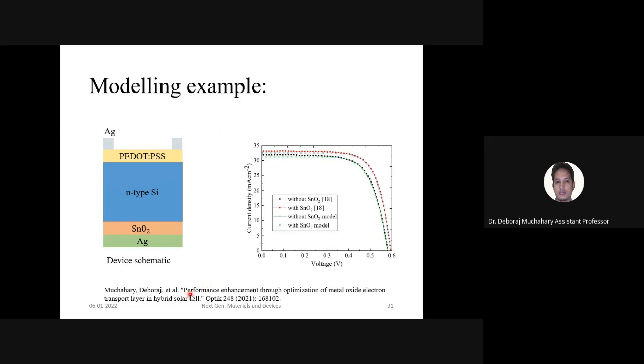Then this is work done by us recently in 2021. Here we have checked the same structure in the simulator. We have used an SnO2 layer at the back side between silver and this side. This was practically done in paper 18; this type of structure was already done. So what we have done is we have matched the simulation curve with the practical curve. These are practical curves, and overlapping is the simulation curve. We have done approximate matching of the simulation with the practical, and we calibrated the device. So the device calibration is done.